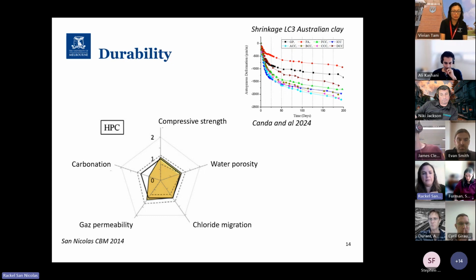And then in respect of compressive strength, water porosity, chloride migration, gas permeation, usually the performance of this type of system is better. In respect of carbonation, as with slag and fly ash, we can have a long conversation about that. It tends to be slightly lower.